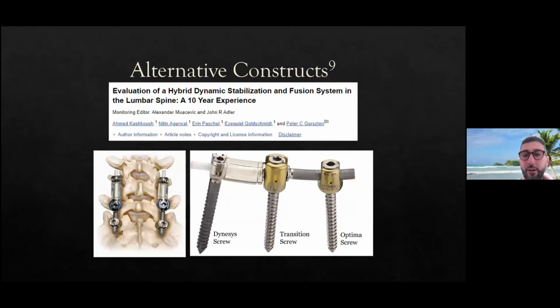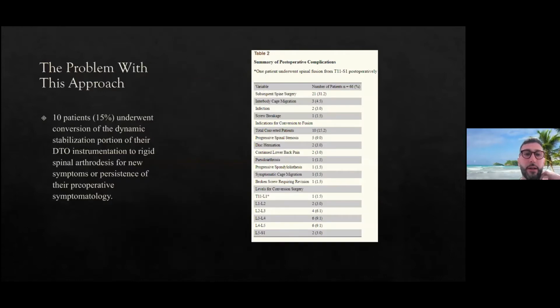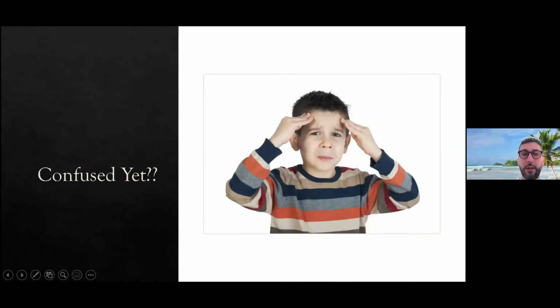This is an interesting one where they were using a rigid rod below at the worst level of pathology, and then a semi-rigid construct above. But obviously every solution has its own problems. In this particular study, 15% of them had to have their dynamic stabilization converted to a rigid fusion, and actually 31% of them had subsequent spine surgery. So, if you're confused at this point about what the right answer is in terms of stiffness of rod, that's good. It means you're starting to understand the problem here and why there are so many potential solutions.